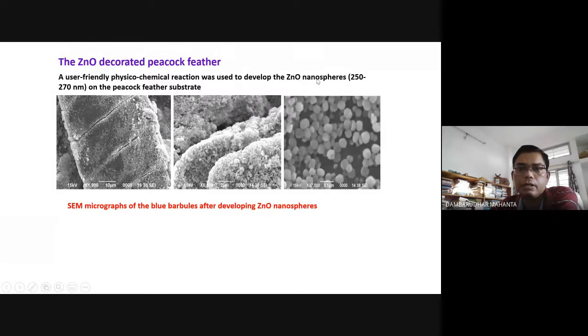So these zinc oxide nanospheres, as I said, because the top layer was keratin, these keratin layers interacted with zinc 2 plus and they form some sphere-like structures. You could see, and this is from cross-sectional view, you could see nicely decorated nanospheres of zinc oxide on the keratin surface. So these are very interesting aspects that we can look at, because the materials are already available in nature and we can manifest with little technique so that we can obtain very nice pictures and modify the properties.